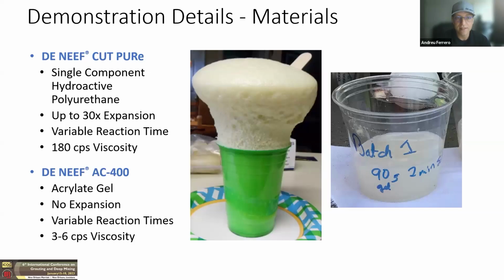DE NEEF AC-400 is an acrylate gel, the picture on the right. There is no expansion in this product. It has a variable reaction time depending on how much and what type of catalyst is used. It has a viscosity around 3 to 6 centipoise. So it's going to be much lower viscosity than the polyurethane. It's going to be able to penetrate tighter soils and tighter defects.